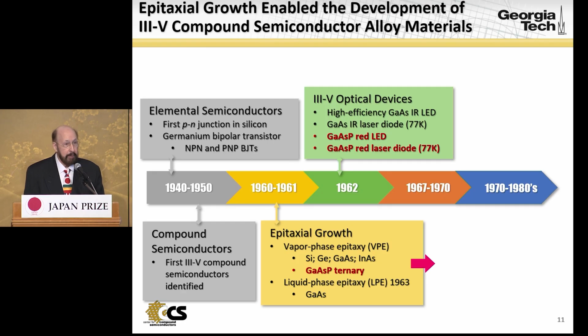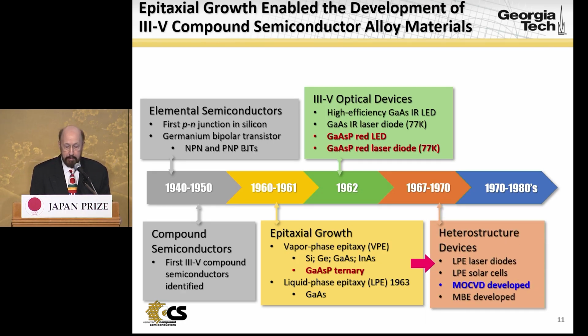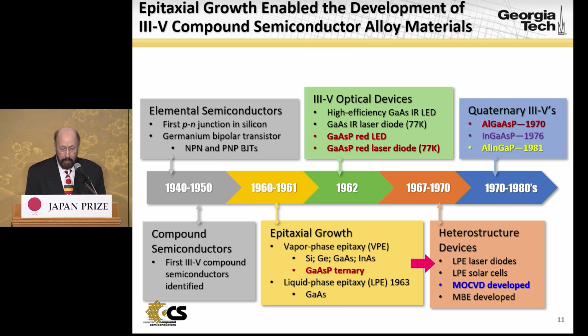This development of epitaxial growth led to rapid development in the period 1967 to 1970 of heterostructure devices using liquid phase epitaxy, for example, for laser diodes, and heterostructure solar cells in gallium arsenide. Also in this time frame, MOCVD was developed in 1968 and MBE about 11 months later in 1968. The next period saw rapid development of the use of epitaxy for the growth of semiconductors, including the first quaternaries, aluminum gallium arsenide phosphide in 1970 by LPE, indium gallium arsenide phosphide in 1976 by LPE, and aluminum indium gallium phosphide in 1981 by MBE, and then a year later by MOCVD.